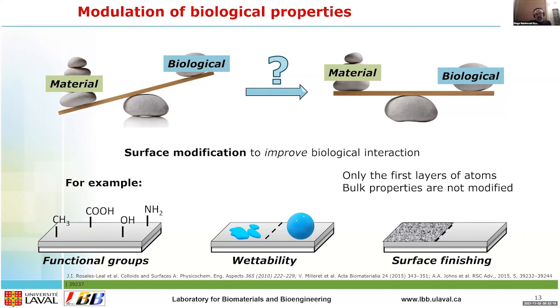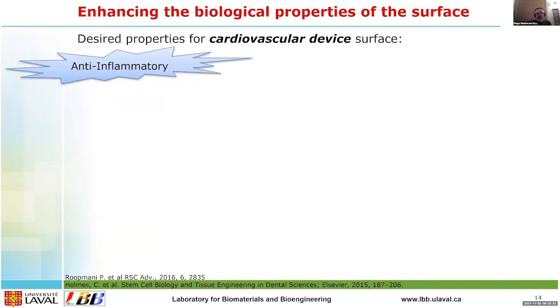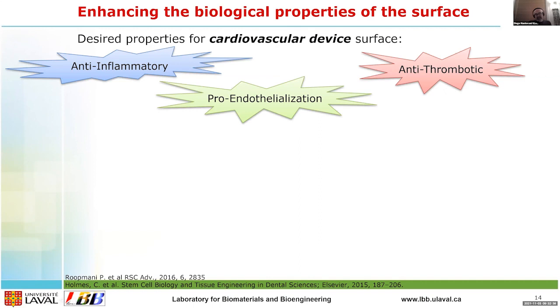So the idea is to change the surface properties, for example wettability, using functional groups directly implanted inside the metals. So no polymer coatings, because polymer coating has the tendency to delaminate when stretched, when the material is deformed. And so the idea is to put together 3 features: pro-endothelialization, anti-inflammatory, and anti-thrombotic. Do you remember I said that bare metal stents are pro-endothelialization, but often coagulate, while drug-eluting stents never coagulate, but also never endothelialize.